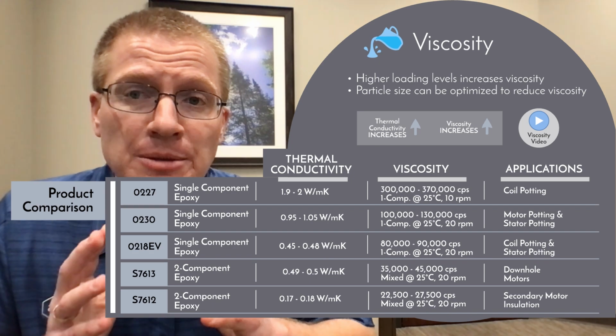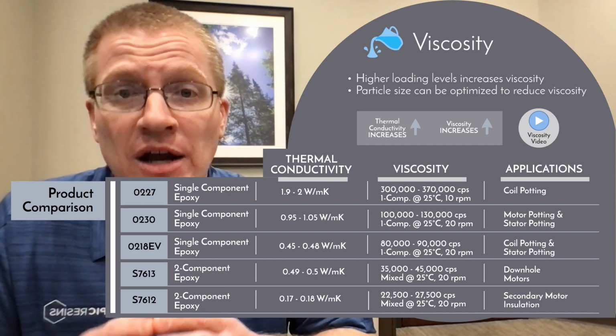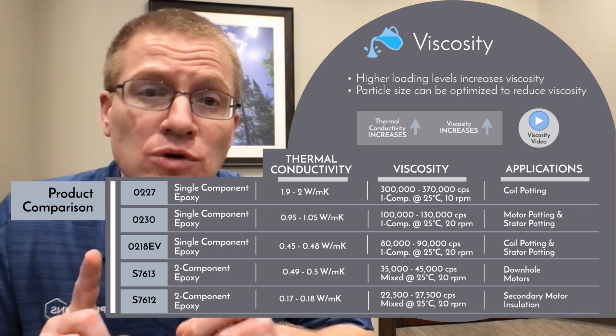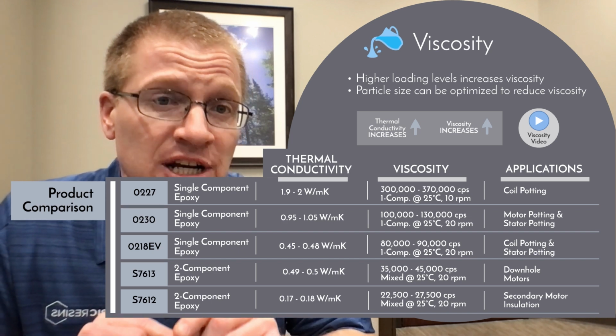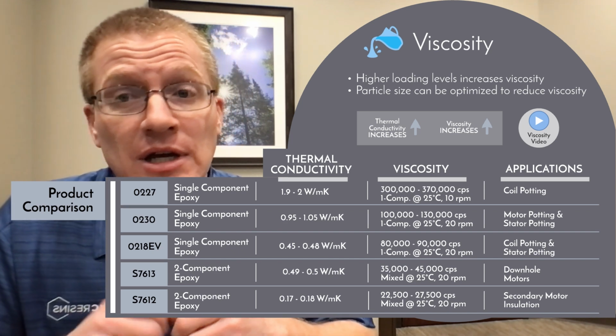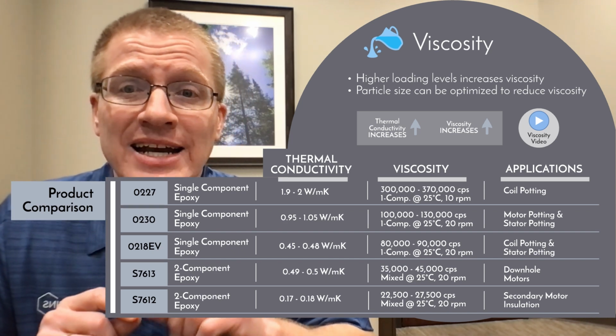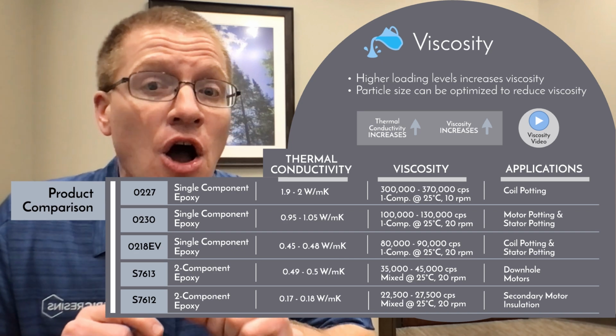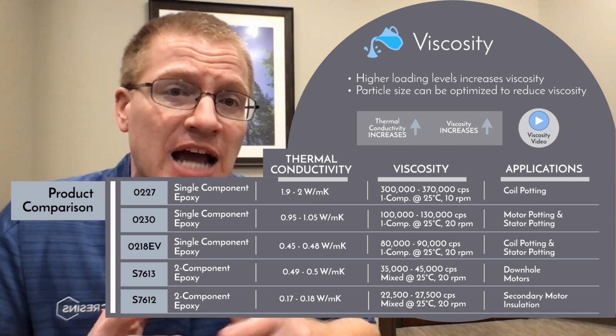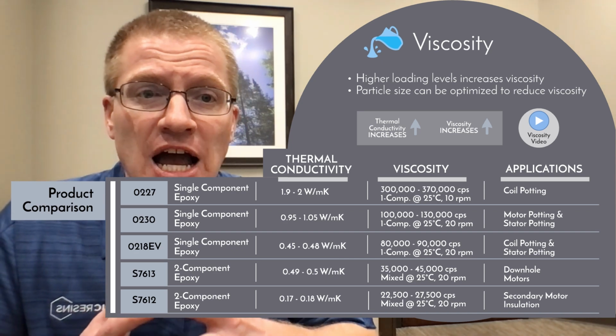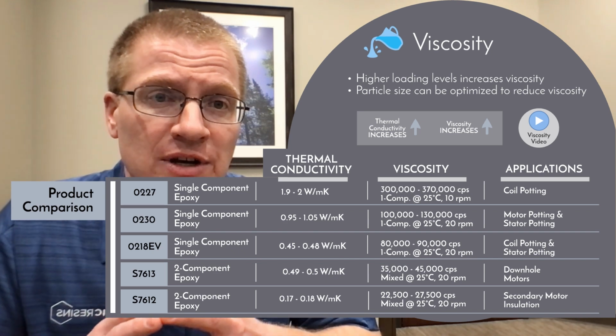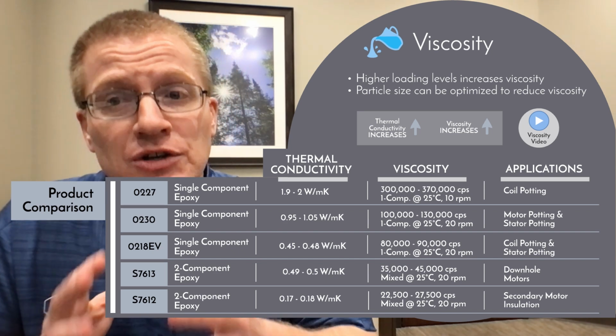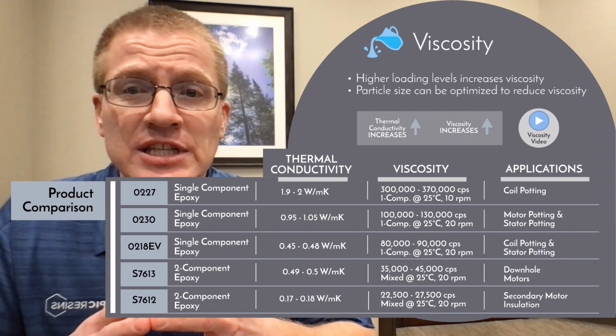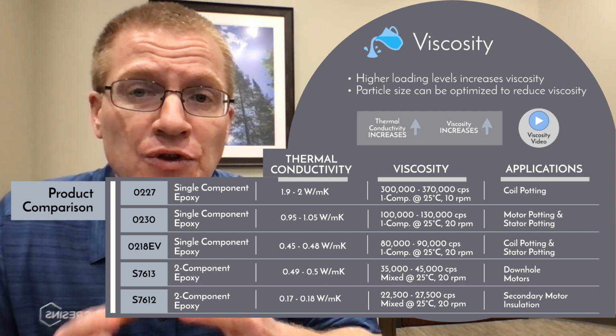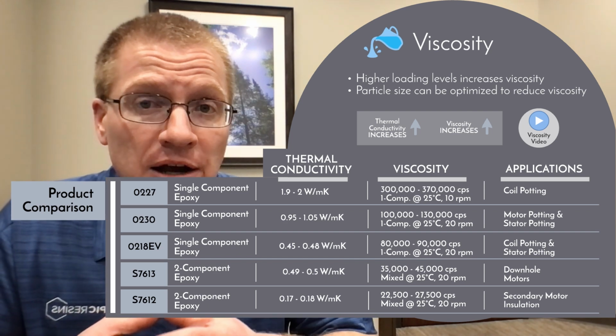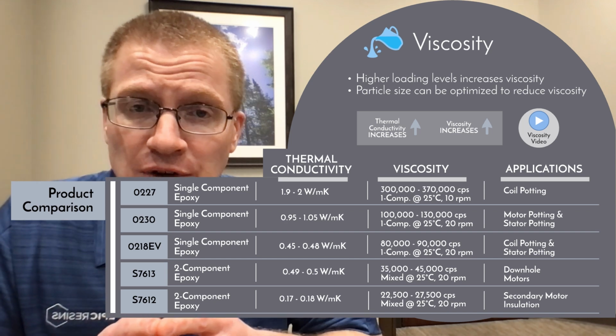As we discussed during the power electronics portion of this webinar, viscosity and flow are crucial to ensuring encapsulation and protecting your components. However, we also learned that an increase in thermal conductivity also results in an increased viscosity. Looking at the viscosity of O227 in the table below compared to the O230, you can see that the viscosity is more than double for the O227, but so is the thermal conductivity.